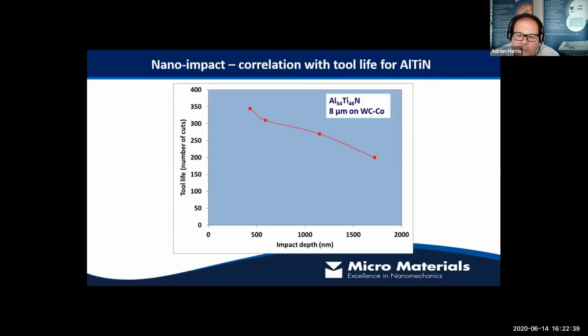So how do we use it to relate to cutting tool life? Here we've got an example. We've been using this technique for at least 15 years now, so we've got a lot of really nice examples where the technique can be used as a really good indicator of performance. Here we've got four aluminium titanium nitride coatings. They're quite thick, 8 microns thick, and they're on a tungsten carbide substrate.